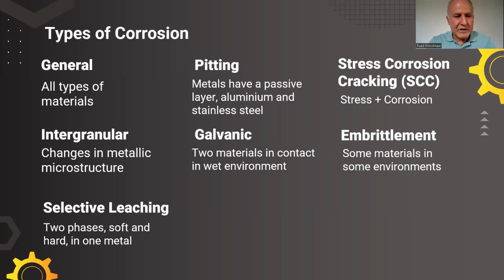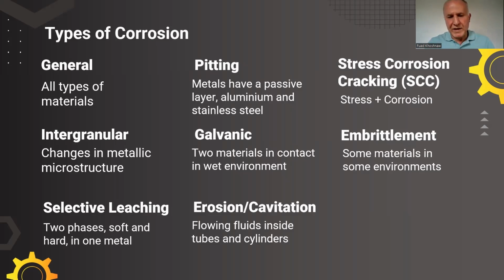Selective leaching: when there are two phases, one of them soft and another hard. For example, as we said in the beginning, one phase is ferrite and another is cementite. Cementite is hard, ferrite is soft. If there is fluid flowing inside, this causes the soft ferrite grains to erode more easily than the hard ones. These different corrosion rates in the same component cause big pits on the surface. Erosion happens when there is a fast flow of fluids going inside tubes and cylinders, so it is somehow a mechanical action combined with chemical.